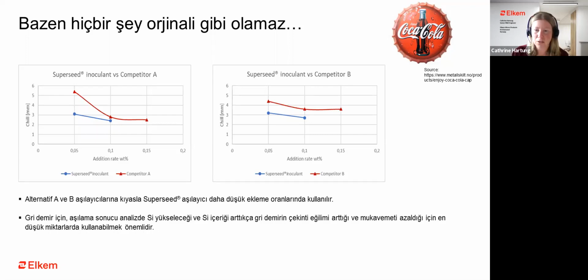And in this case, you see here an example where we have tested two of them, presented together with the results for superseed, and where we have varied the addition rate. So in the left figure, we have inoculant A versus superseed, as a function of addition rate. At the 0.1 addition, we are adding this in a small ladle and holding it for about 1 minute before we pour it. So it's equivalent to a ladle addition.